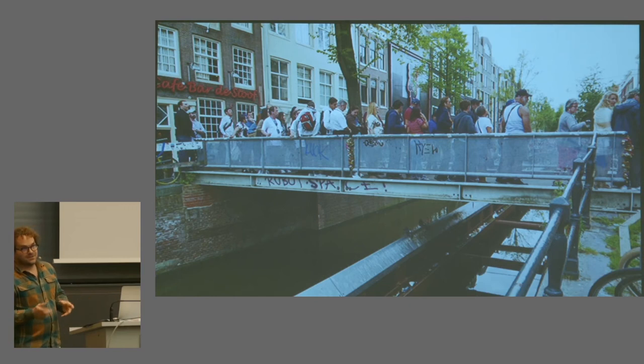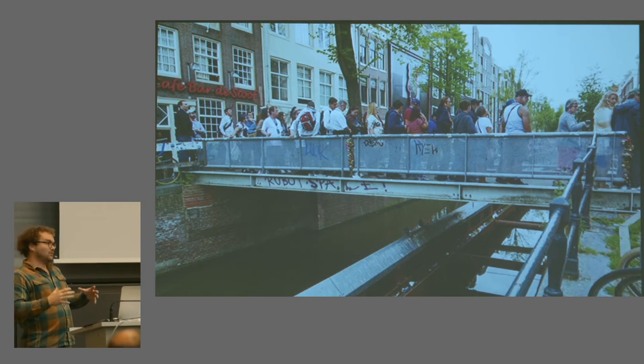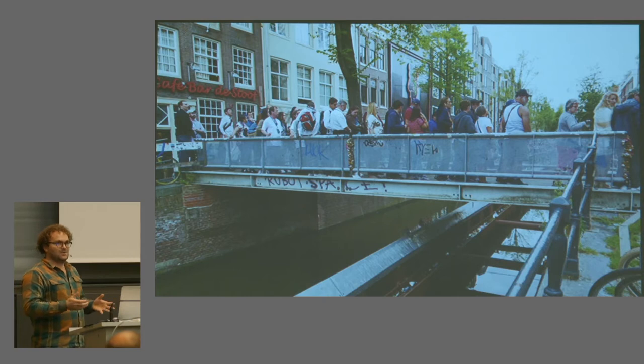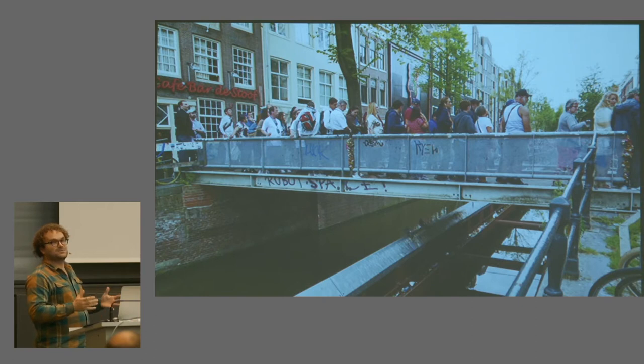So that's also what we did in Twente just this month with Imperial College and Twente University. We put 20 tons on it. It maintained perfectly, so that's, I believe, 1.3 times the maximum load capacity that we needed to go for. And then to test our assumption, to see if that in real life would be sufficient, we put as many people on as we could, and that was around 90 people, 6-7 tons, I think. So we feel that we concluded a nice conclusive test about the stability of the bridge.